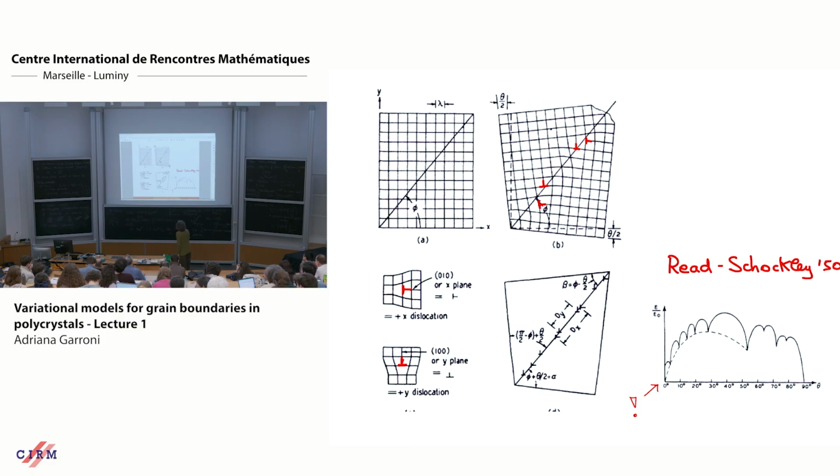And so the computation I want to make today is about this derivation. It's trying to give you a model, which will be a diffuse interface model, which will possibly contain some physics that explains why, if you see the grain boundaries in this way, you obtain this shape, which is sort of the energy per unit length. This is the shape of the possible energy depending on the angle at which you tilt the two interfaces. And you see, in this picture there is a sort of infinite slope at 0. And this infinite slope has a specific structure. I didn't write it here, but it is, say, theta log theta. So I want to give you a model which has some physics to explain why at this small angle grain boundary you have this theta log theta.